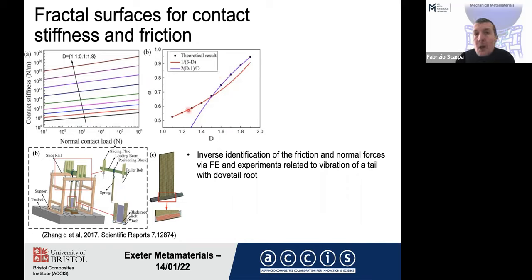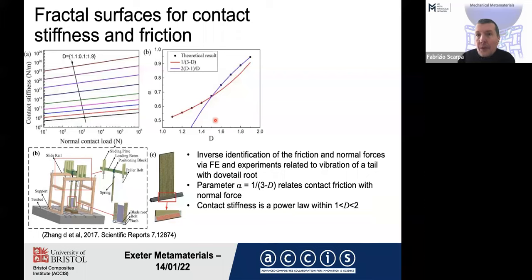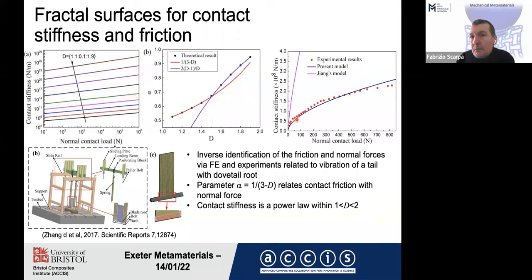We also modified the model to consider this parameter alpha that relates the contact stiffness to the normal force. And you can see there is a good agreement, but the take-home message is the contact stiffness follows a power law for this type of fractal surface. So you have this type of power law that transmits the topology of the fractality, but also, if you want, the shape of the matrix or the mechanical response that you are looking at.